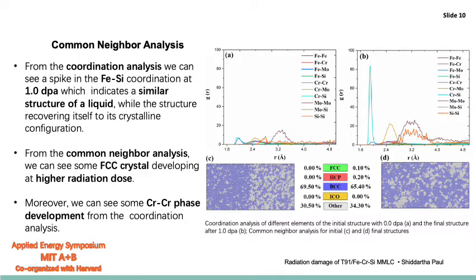The common neighbor analysis of the structure has shown the structural rearrangement of the iron chromium, silicon chromium, and chromium molybdenum neighboring atoms after implementing a certain amount of radiation dose. The structural rearrangement of the chromium and its neighboring atoms in this particular MMLC interface actually suppresses the defect formation and the interface thickness at higher radiation dose, because this particular rearrangement happens at the higher radiation dose. So that's why we have seen that the interface thickness and defect formation become saturated beyond 0.2 dpa.